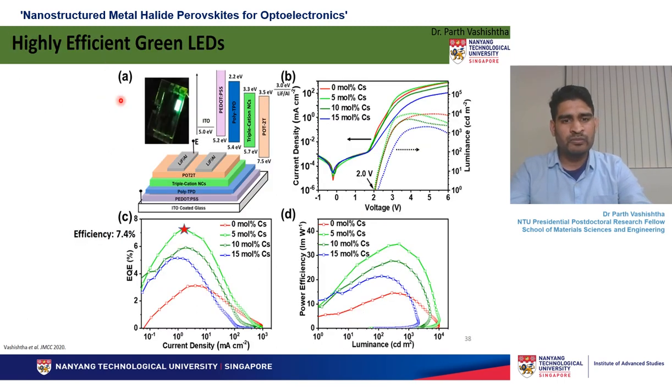And then we used these nanomaterials to build the LEDs, using a similar structure to what I explained earlier, spin coating and spin coating the perovskite. And we saw one of the lowest turn-on voltages in these materials. The LEDs turned on at 2.0 volt, which is really low compared to existing perovskite LEDs. All of these materials showed very high brightness, close to 10,000 candelas per meter square,